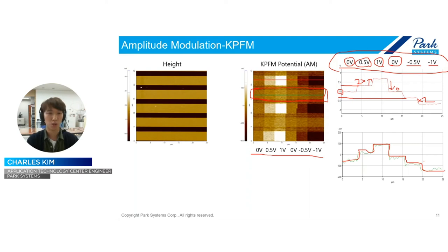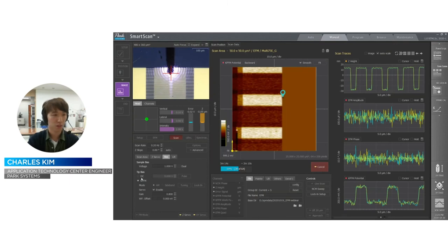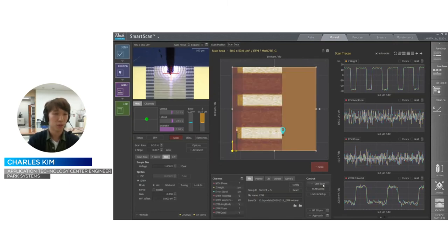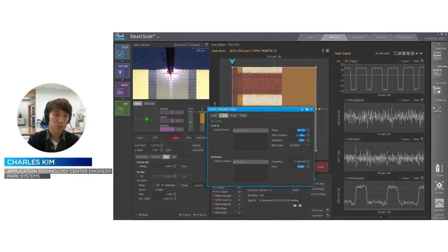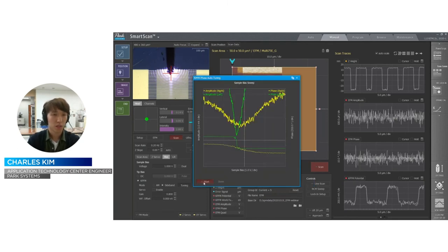So let me show you then how to measure the sideband KPFM. The sideband KPFM is also very simple. To do the sideband KPFM, just change the scanning mode here to sideband. And also, previously the amplitude modulation KPFM used 17 kHz. But in the case of the sideband, we just use a small value of frequency, for example, between 2 to 5 kHz. So let me use 3 kHz this time. And after that, click the tuning and click the start.